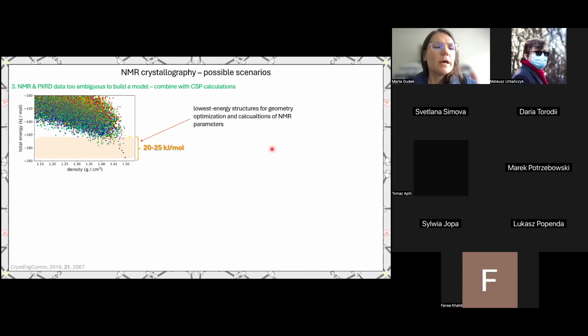And finally, it is also very much possible and often encountered that neither NMR nor powder X-ray diffraction data can give you an appropriate model to calculate and evaluate. So in these circumstances, we often use crystal structure prediction calculations, which generate hundreds of thousands of crystal structures. What you see here is the result of such calculations: a plot of the total energy of crystals against density, and each dot on this plot represents a different crystal structure. So we can generate and then energy minimize many such crystal structures. This is, of course, computationally expensive, but we can use experimental data to narrow down the search space that we need to cover.